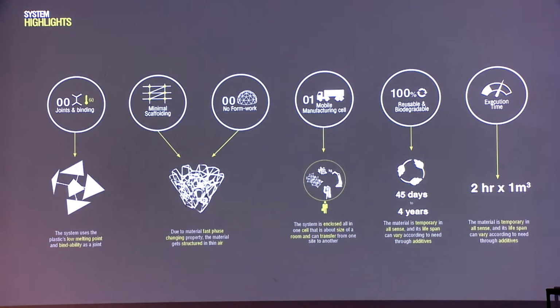The fabrication process is aimed to be as simple as possible. So in summary, our system can produce structures that are jointless and self-bindable, with minimum scaffolding and no formwork needed. All the manufacturing process is done in a mobile cell, and once the units are no longer in use, they can either be shredded down, refit into the system, or left to biodegrade. The biodegradability of the material can vary according to usage, from 45 days to 4 years. Approximately, it takes 2 hours to produce 1 cubic meter of space with our material.